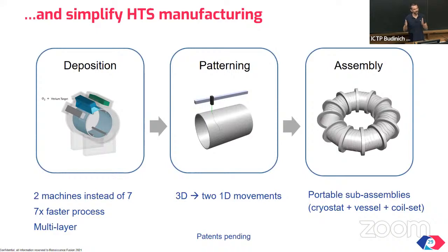These grooves bound the current. When you energize these coils, the current will follow a specific pattern as imposed by the boundary conditions by these insulating grooves. One point I would like to stress, there is superconductor nearly everywhere except in the grooves, not the other way around. These are not current filaments, these are current stripes bounded by narrow grooves.